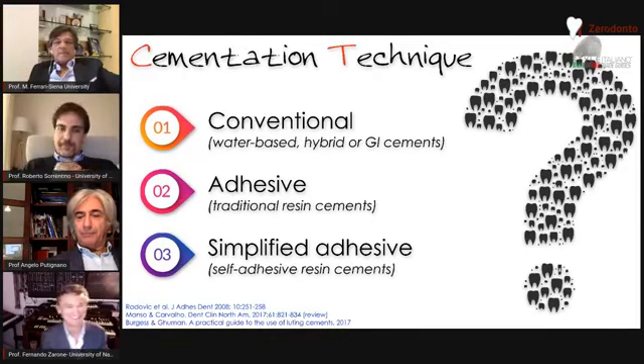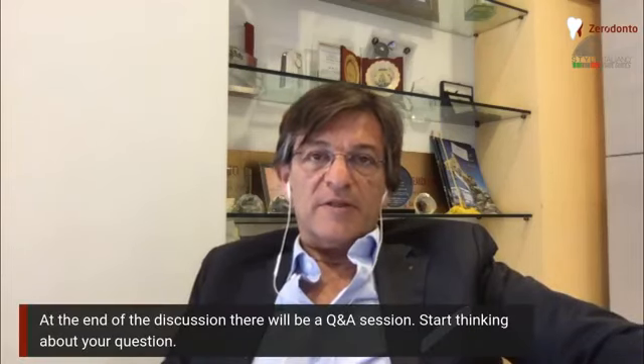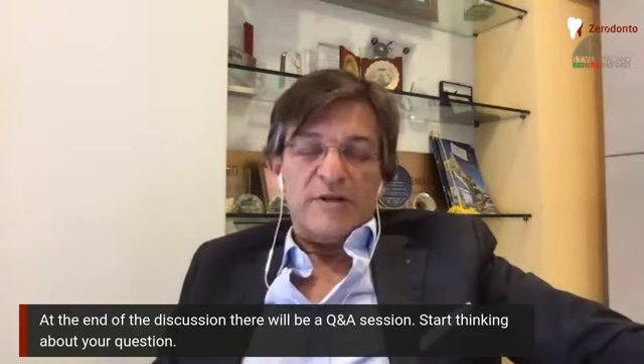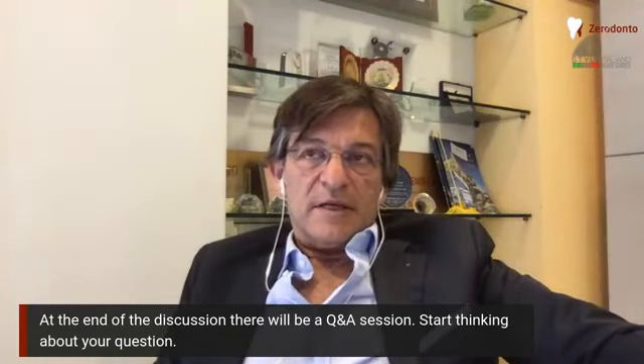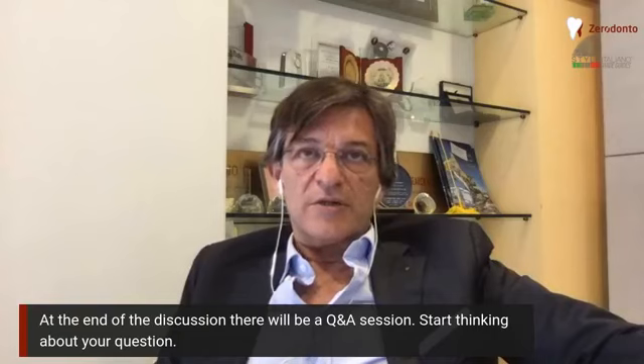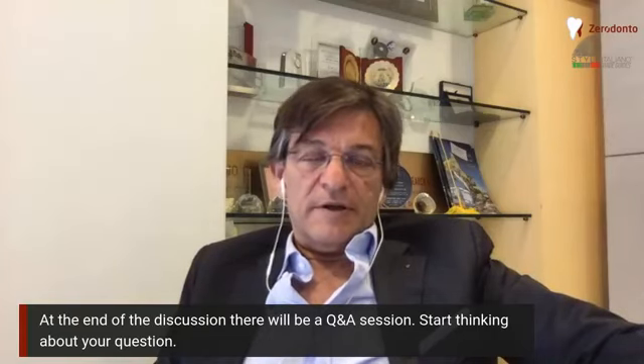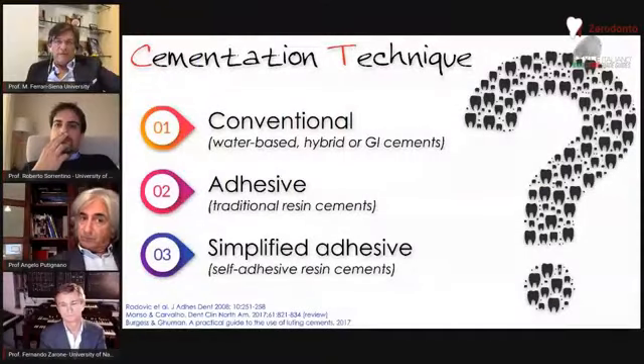Please, Professor Ferrari. Yes, thank you. To me, I would go for adhesive luting material. So bonding and luting with bonding system and a luting material, dual cure resin cement. That is because in literature it seems to be the most reliable for lithium disilicate. And then also during the luting procedure, I can control what I'm doing. And so I would not go for glass ionomer. I would not go for simplified adhesive self-adhesive resin cement.